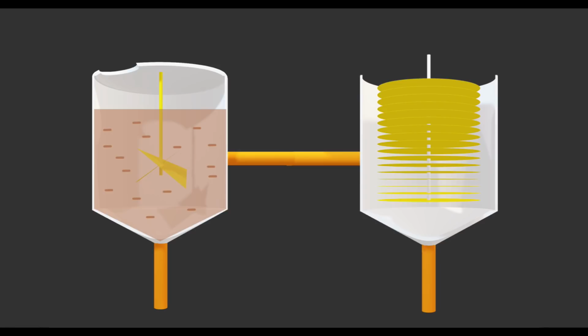Those clay colloids could be precipitated out of solution by a flocculant, such as aluminum sulfate, aka alum. Alum disrupts the negative charge of the clay particulate, which causes it to clump together and then settle out of solution. It's often used by municipal water supplies to remove colloids from water, so it's a cheap, common bulk material. The precipitation removes the clay from the water, making it clear rather than cloudy, which is why this step is called clarification. The clarification step leaves us with two materials.